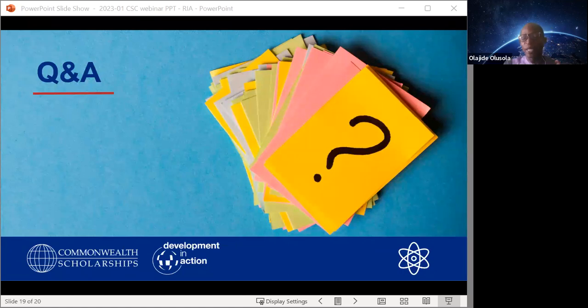So I decided to look at the various literatures. I found out that they used different pH for the electrolyte, the bath. So I did a research to bring together what all these researchers actually did. In a single go, I made different baths and varied their pH, using the same salt composition but different pH. And I found out that all the researchers are actually correct. Based on the pH, I got some red color, some dark color, some dark red.